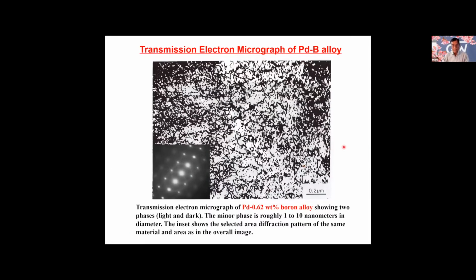And this is some TEM, and again, a lot of work has been done on that, but I'm just showing one transmission electron micrograph for 0.62 weight percent. I must mention here that we aimed to make it 0.75 weight percent, but we ended up with 0.62 actual boron content in the alloy. It may be hard to see, but the small dots are one phase, and then you have the matrix phase. The dots are roughly around 1 to 10 nanometers. And this is a selected area diffraction pattern of the same material and area as in the overall image.